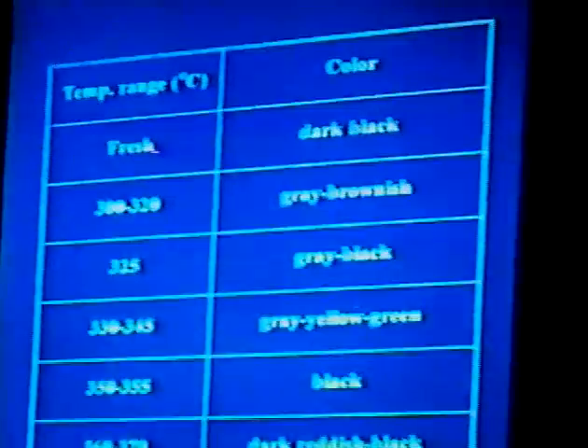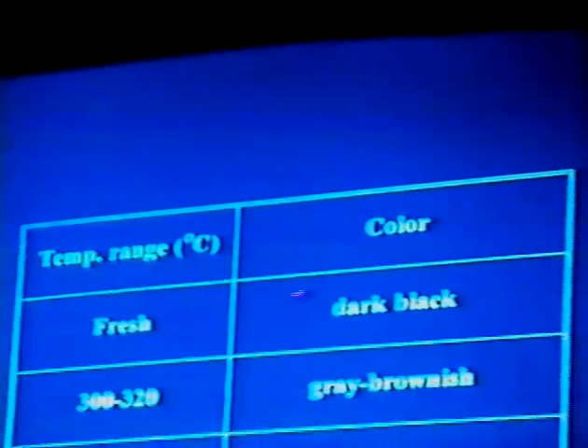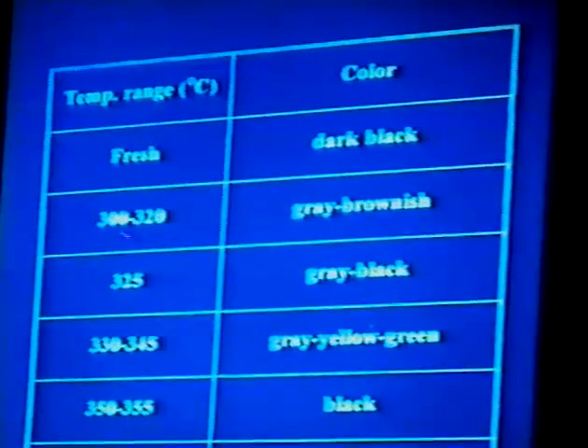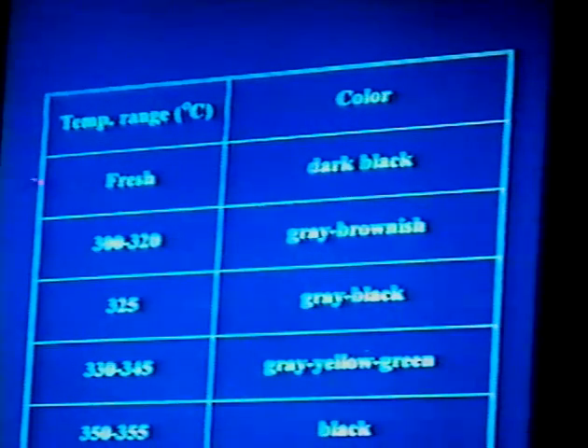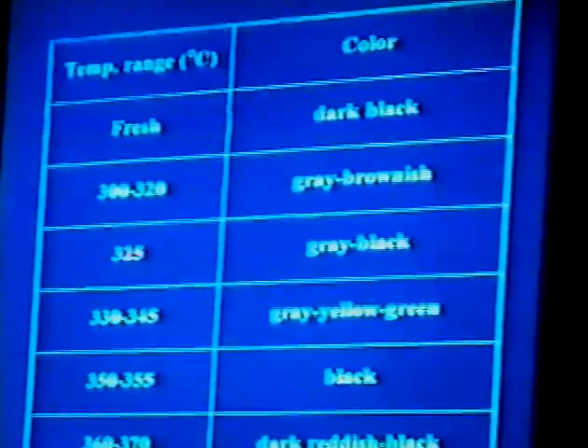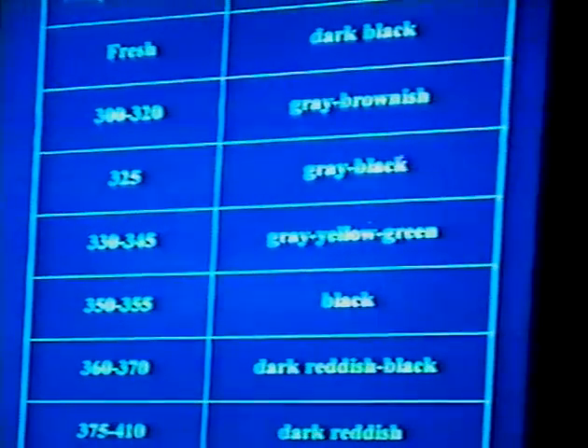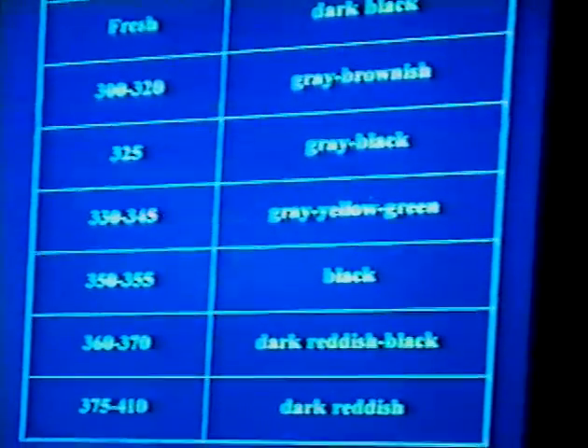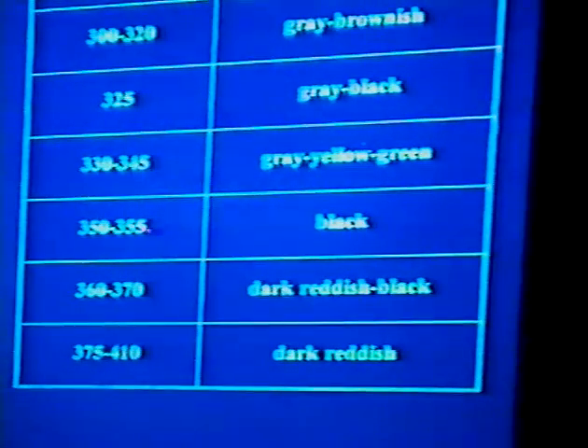First we took the catalyst out of the reactor. You can see the fresh catalyst is dark black. At a temperature of 300 to 320 degrees, with no catalytic activity loss, the catalyst still maintains a brownish color. But at a much higher temperature, you can see the color changing quite quickly to yellow-green. And when we take out the catalyst from above 350, the color comes back to black again. At a much higher temperature, the color becomes reddish again. So what happened here?